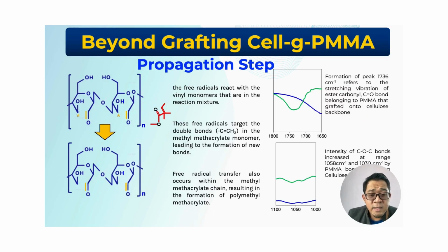And then we go to the propagation step. In the propagation step, the free radical reacts with the vinyl monomer that is in the reaction mixture. This free radical targets the double bond in the methyl methacrylate monomer, leading to the formation of a new bond. The free radical also transfers within the methyl methacrylate chain, resulting in the formation of polymethyl methacrylate.